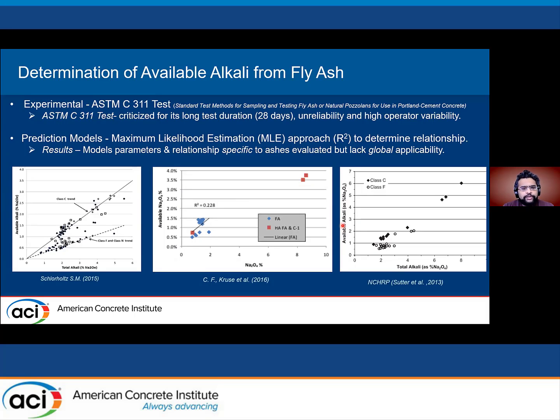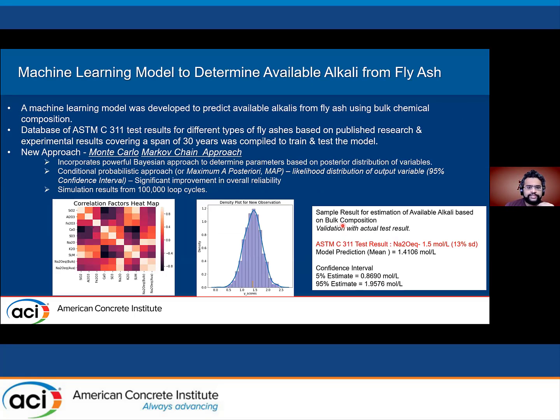Now, determining the available alkalis from the fly ash is usually preferred as an experimental technique, but the test is usually criticized for its very long duration and high variability. The prediction models often rely on the R-square approach, or the least sum of squares. So we have different equations coming from different studies, but the equations perform very well for the local studies or the studied fly ashes, but they do not incorporate a global variability. And that's where the machine learning aspect really comes in handy.